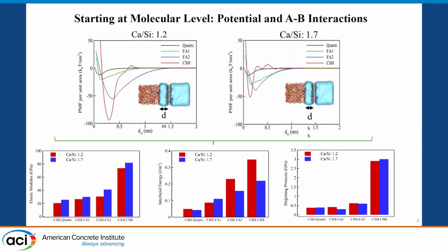So if you would like to improve the interfacial properties, aim at fly ash with a larger concentration of alkalis and cations. At the same time, you also see that the pozzolanic CSH with the lower calcium to silicon ratio is not as effective when it comes to strength, compared to 1.7, in terms of disjoining pressure, interfacial energy, and bonding. So it's always CSH that is the strongest.